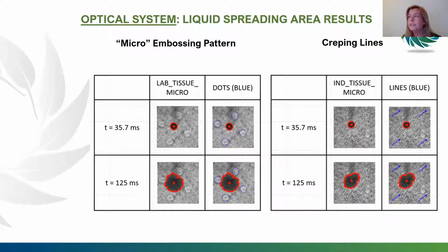In this image, we will see in more detail that the absorption properties are modified due to the creation of 3D effects on these structures. In the image on the right, we have the creping lines here in blue. So the creping lines direction is indicated in blue, and the spreading shape of the droplets reflects the influence of the creping operation in the structure. In these images, the bigger axis of the elliptical spreading area is located along the creping lines direction, indicating that the creping has an influence on the tissue paper structure and consequently on the water spreading anisotropy.